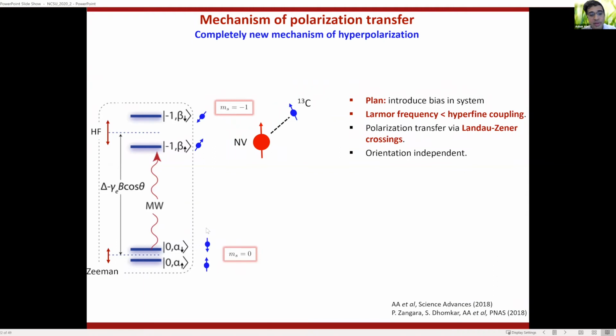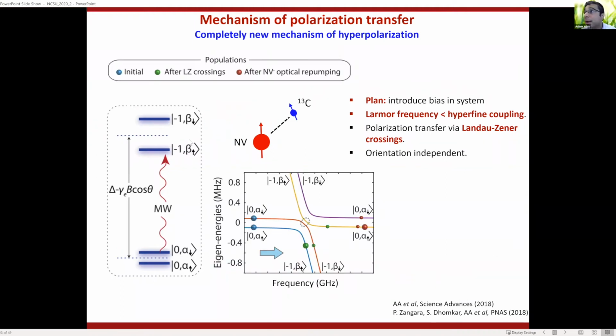And that's what happens. It turns out if you write down the same energy structure in the rotating frame, and this is a picture in the rotating frame, as you sweep the microwaves, you get these level anti-crossings. And the fact that you get level anti-crossings is not surprising, but what's interesting is that you get level anti-crossings for which the energy gap is a function of the spin state. So if you start with the spin state up here, you've got a large energy gap. And if you start with the spin state down, you get a small energy gap. And all of us know that if you traverse an energy level anti-crossing, the traversal can be adiabatic or diabatic based on the size of the energy gap. And if you're adiabatic, you more or less remain within this branch. But if you're diabatic, you split the population between the two branches.